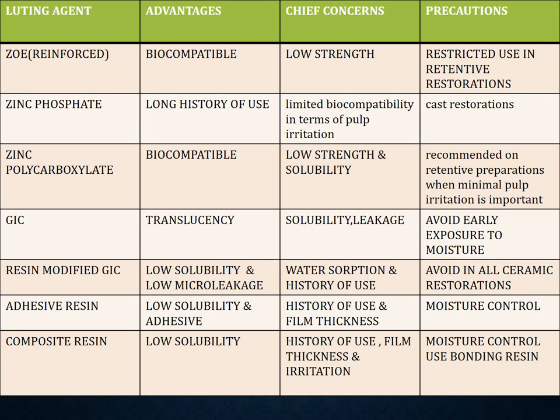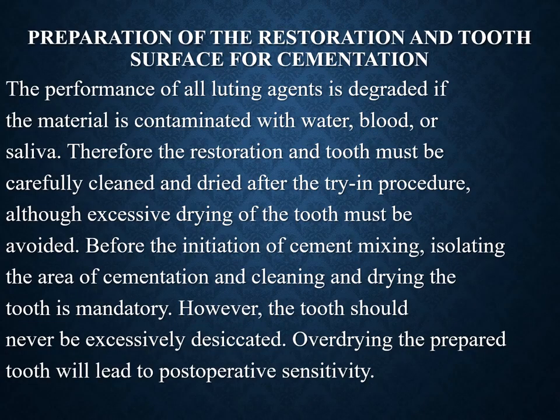There is a summary chart listing luting agents, their advantages, chief concerns, and precautions to be taken — you can refer to it for a quick overview. The performance of luting agents is degraded if the material is contaminated by blood, saliva, or water; therefore the restoration and tooth must be carefully cleaned and dried after the try-in procedure. Isolation of the cementation area and cleaning and drying of the tooth is mandatory before initiating cement mixing; however, the tooth should never be excessively desiccated, as this can lead to post-operative sensitivity.